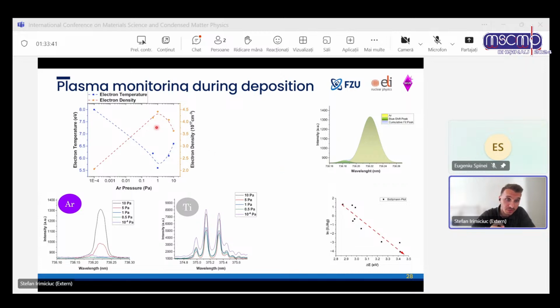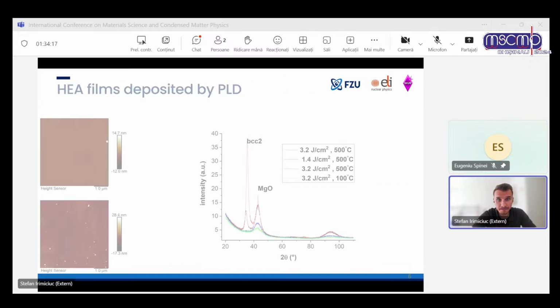But what was curious for us is that the electron density and the electron temperature had a sort of strange behavior. We expect normally, with the addition of pressure, as you saw before, maybe some monotone increase, and then a saturation, or just a decrease. But actually we see that there's a turning point in the evolution close to 1 Pascal, where something changes in the plasma, and that means for us that maybe after 1 Pascal we have some changes in the films.